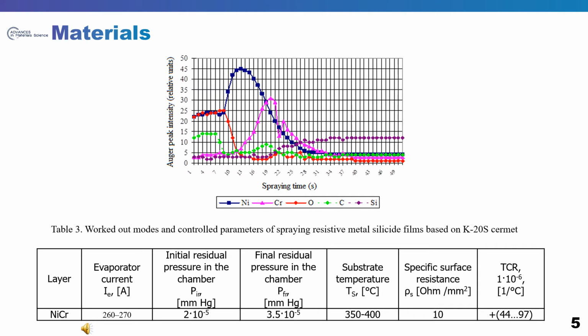According to the source, the distribution of elements over the thickness of the thin film due to the fractionation of the alloy is presented. The analysis was carried out by the method of Auger electron spectroscopy. Pure chromium lies on the surface of the dielectric layer, the ratio of nickel to chromium changes closer to the center of the film, and nickel coated with oxide lies on the surface. Over time, the final formation of phases and recrystallization, on the one hand, and surface and bulk oxidation of chromium, on the other, are possible.